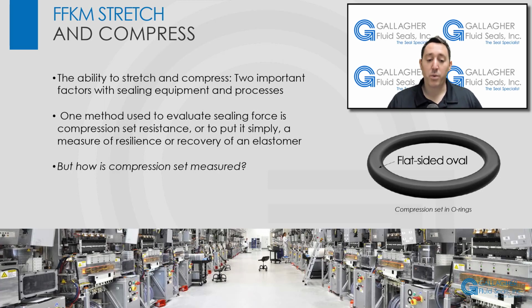Since most Kalrez parts are used as sealing elements, the retention of adequate sealing force over a long service life is an important property. One method used to evaluate sealing force is compression set resistance, or to put it simply, a measure of resilience or recovery of an elastomer. It is a useful preliminary quality control test, but not necessarily a good indicator of service life, since it does not reflect three areas of concern: long-term use, actual application temperatures, or the effects of aging.